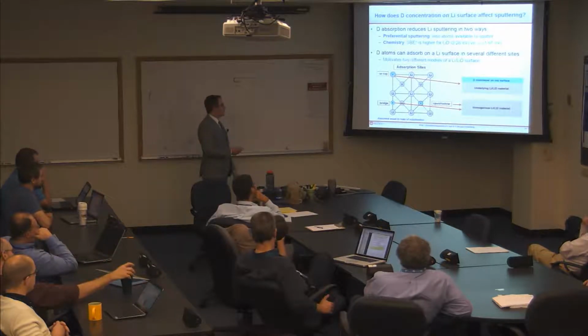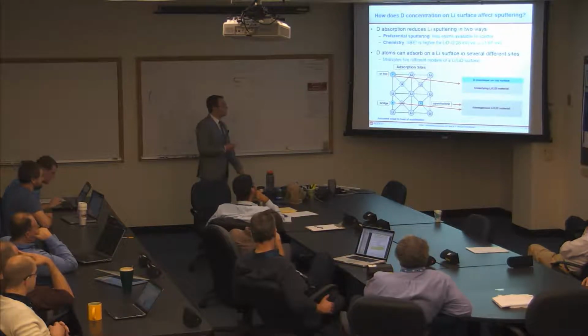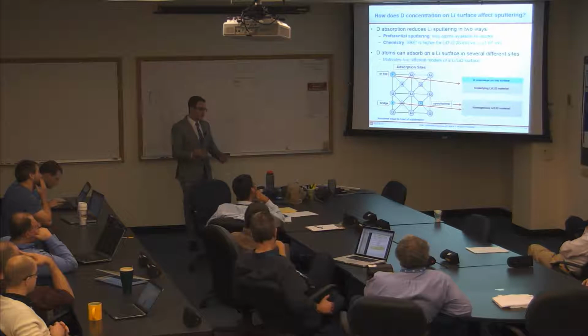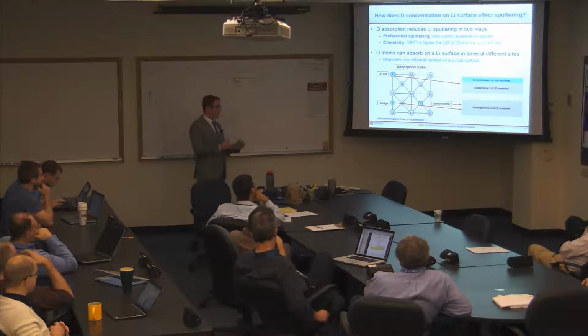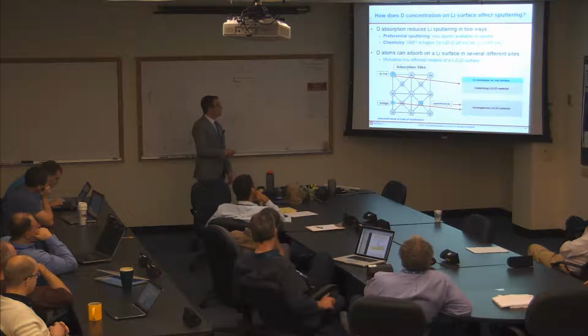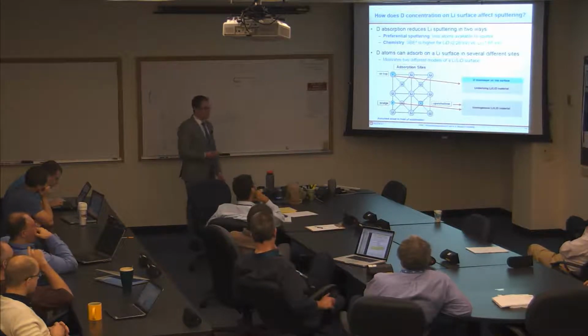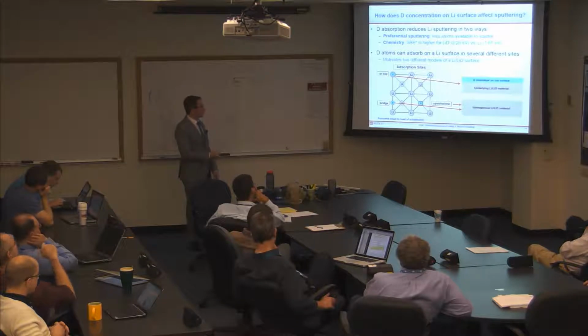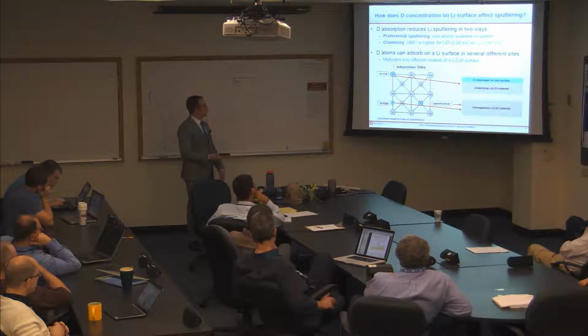This is referred to as chemical sputtering, and it essentially results because the surface binding energy, which is some metric for how closely the surface atoms are held into the bulk material, is higher for lithium deuteride than it is for pure lithium. And typically, in sputtering calculations, you assume that the surface binding energy is equal to the heat of sublimation of the material.